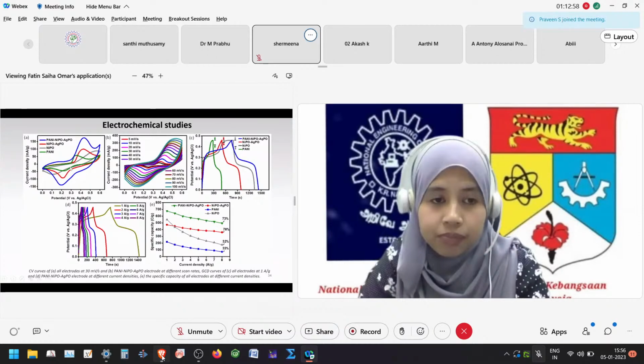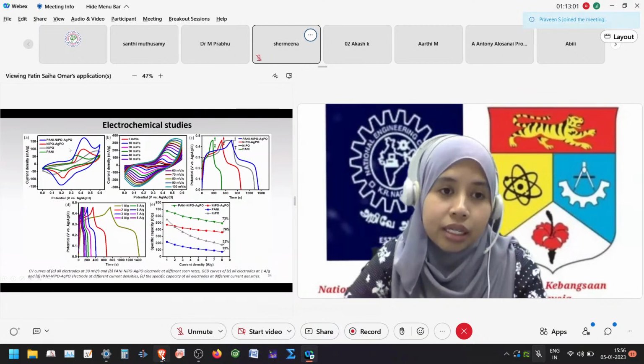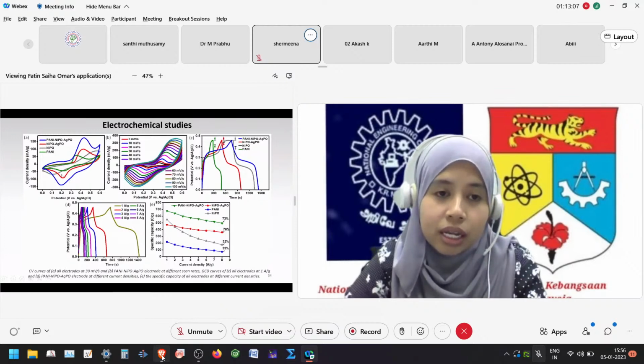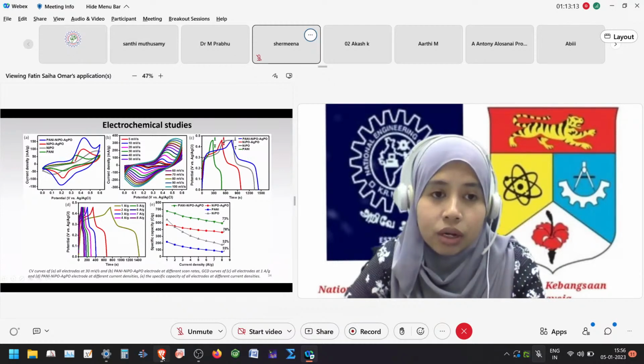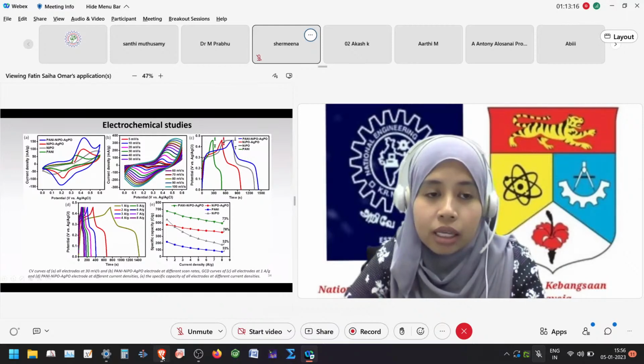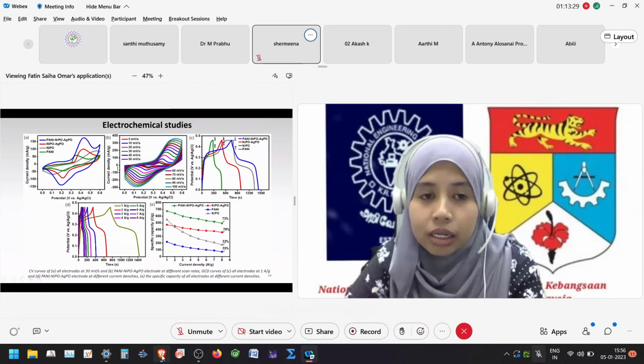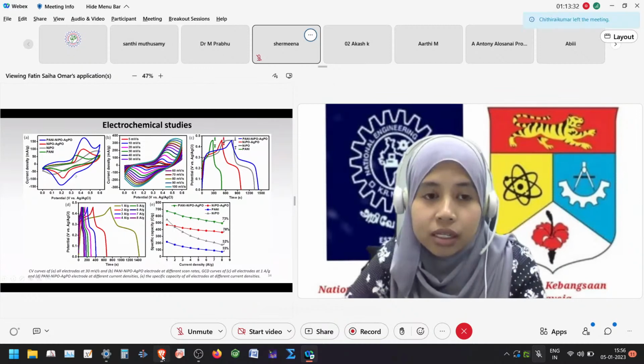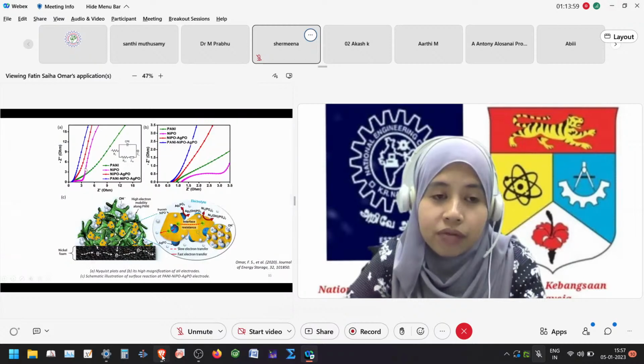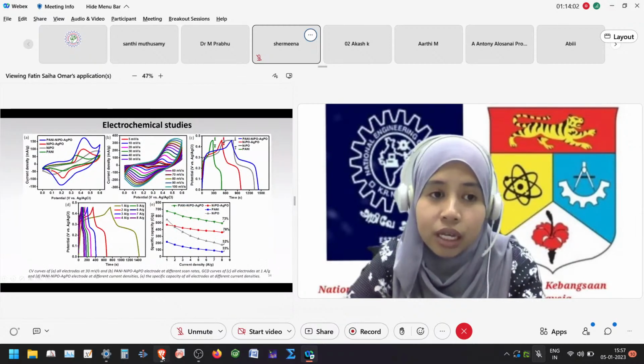Okay, so in this figure, the polyaniline nickel phosphate silver phosphate has the largest CV area. So it means that it has the highest specific capacity, but it depends on the weight of the active materials. So in this case, after we take into account the mass of the material and then calculate the specific capacity, the polyaniline nickel phosphate silver phosphate really has the highest specific capacity. And what we can interpret from this figure is that a diffusion process is happening during the charging at the anodic and discharging at the cathodic.